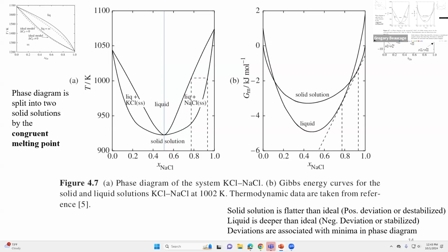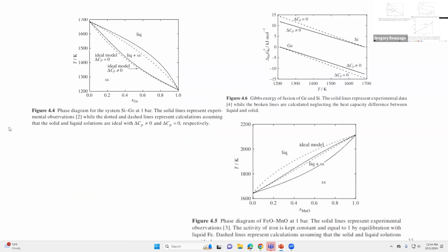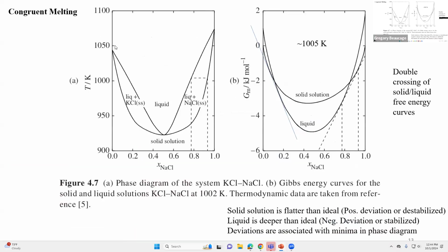But there's these simple solid solutions where the two crystals, germanium and silicon, both are diamond cubic. They're roughly the same size, they fit in the same lattice, roughly. So they're completely miscible over the whole range with the same crystal structure. The lattice constant a will shift as you go across composition, but basically it's the same crystal, so it's the same phase that's in equilibrium with the melt of these two semiconductors. And so they form this kind of solid solution phase diagram.